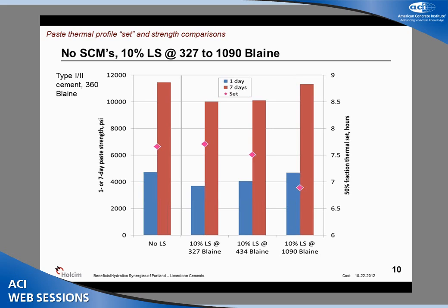I've tried to dumb this down to just a few to show some trends. But this is a trend that we see with ordinary Portland cement, no SCMs involved at all, with simulations of 10% limestone cement. And we varied the fineness of the limestone to better understand the influences there, all the way from a fairly coarse limestone, significantly coarser than the cement that we're using, to a very fine limestone that we frankly thought was probably in the neighborhood of what the Portland limestone cement system was actually, if you could delineate the limestone. And here's the performance: 1 and 7 day paste strengths.